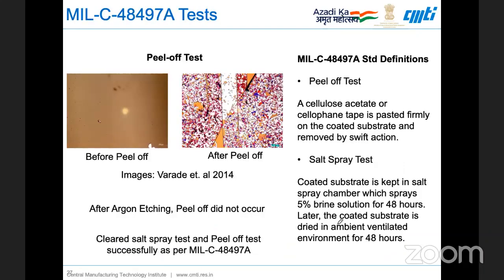So these are peel-off tests, which are required when you want to prove it on applications such as night vision, where you have to show whether it peels off or not. This is work from a paper by Varade et al., which shows a germanium wafer on which diamond-like carbon is coated, and a microscopic image of how it looks when you peel it off. But on our films, the peel-off did not occur, and we have also cleared the MIL standard test as per MIL C48497A. So we have already cleared all the tests, and it does not peel off. It is as robust as far as adhesion is concerned.